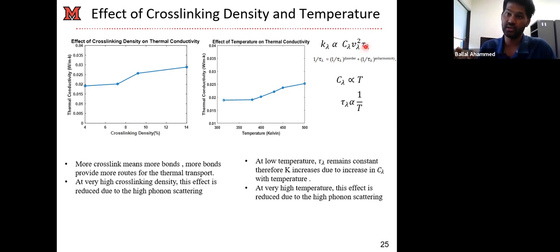So a higher relaxation time means that your phonon can travel more distance without being scattered. That also increases the thermal conductivity if you have a higher relaxation time. We know that the specific heat is proportional to the temperature, and the relaxation time is inversely proportional to the temperature, because when you increase the temperature to a very high degree, it reduces the time between two successive collisions or two successive scattering events.